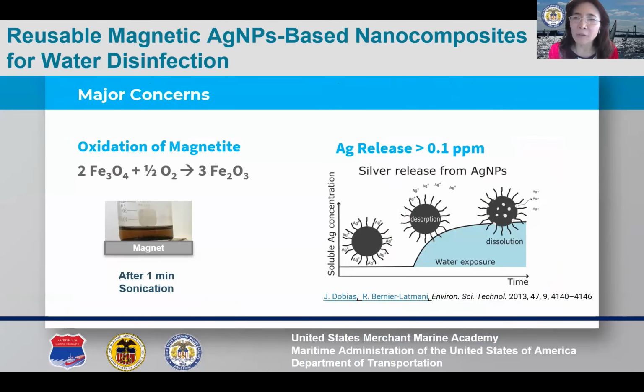However, we noticed that after multiple repeated uses, the nanocomposites became less responsive to the magnetic field, significantly decreasing their recovery rate. This was attributed to the oxidation of the iron 2 ions by dissolved oxygen in water to the much less magnetic iron 3 oxide. Additionally, for silver content greater than 0.22%, atomic absorption, or AA spectroscopy, suggested a potential silver release above 0.1 ppm. Both are big issues concerning the product's reusability.